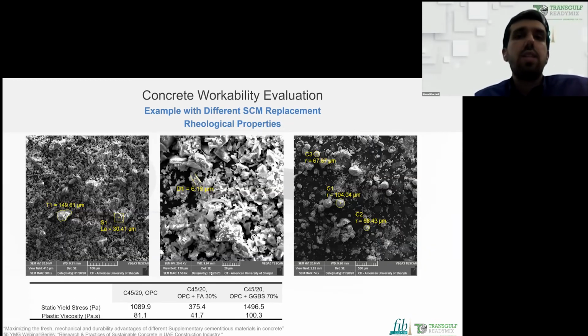And this is actually for the material used in the study, and these are scanning electron microscope photos of the material. You can see that the GGBS, the ground granulated blast furnace slag, has granular particles with sharp angles. These particles will have friction between each other and with the ordinary Portland cement, and will make the concrete a little bit more viscous compared to the Portland cement. That explains the higher static yield stress, which is the stress required to initiate the flow in the mix.